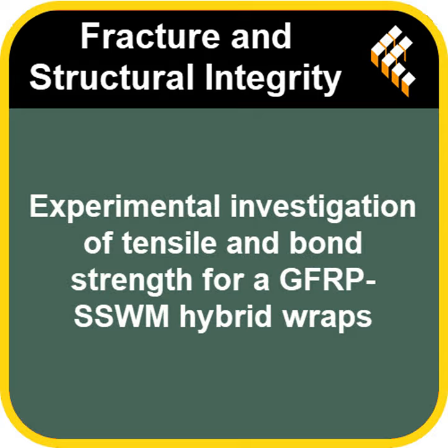Because if the wrap doesn't stick to the structure it's supposed to strengthen, then the strength of the wrap itself doesn't matter much. Precisely. So those dumbbell specimen tests were key, and they confirmed what we saw in the tensile tests, really. How so? The hybrid wraps, GS and SG, generally showed higher load carrying capacity and better bond strength compared to pure GFRP or pure SSWM wraps.